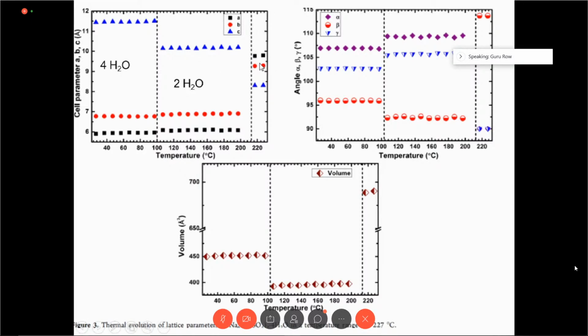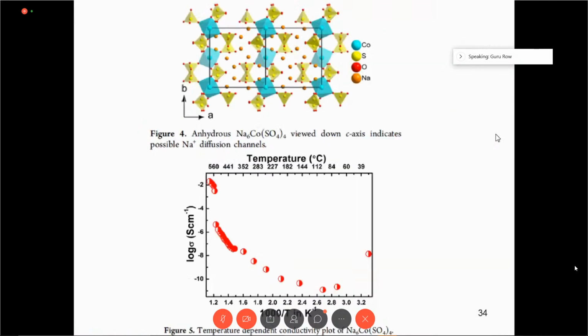And this is indicated in terms of the cell parameters, in terms of angles, and in terms of volume when we see the X-ray diffraction. The structure of the anhydrous sample has been determined at the high temperature structure, and that happens to be this. We see that again we have the sodium ion channels.